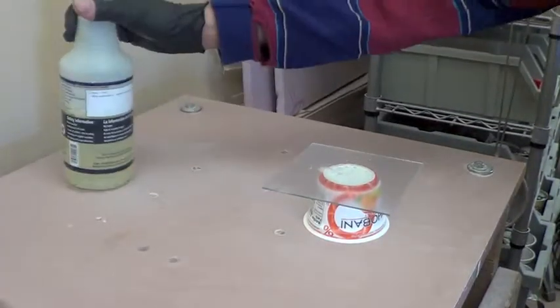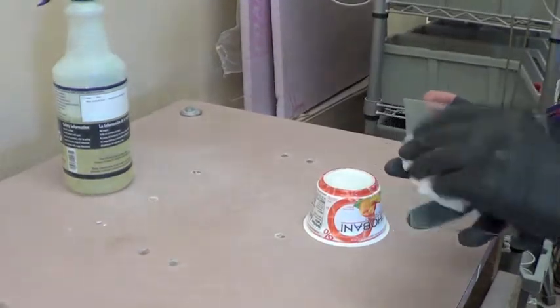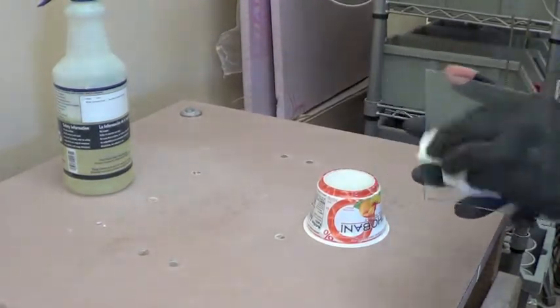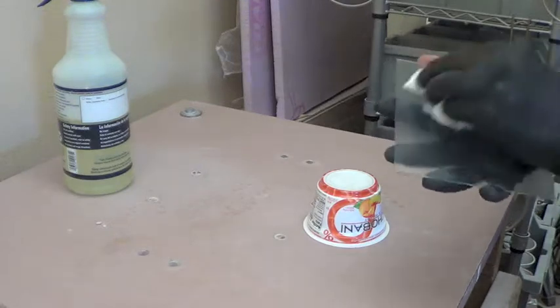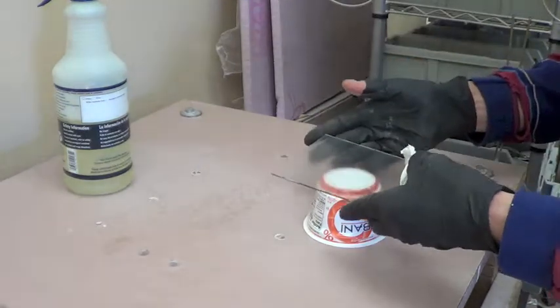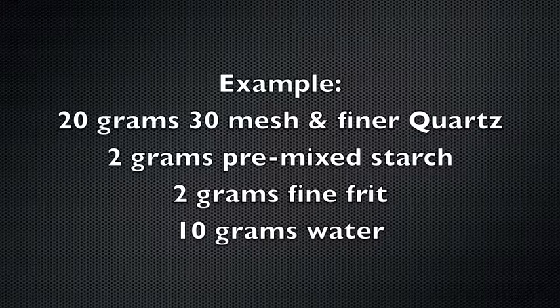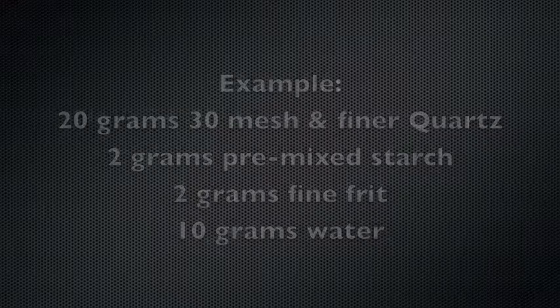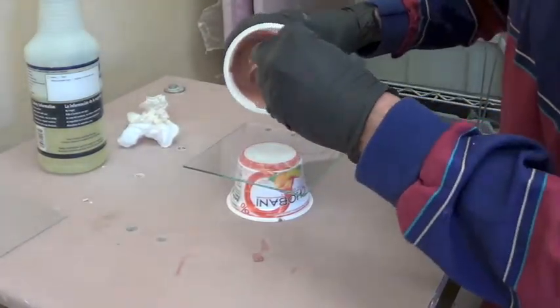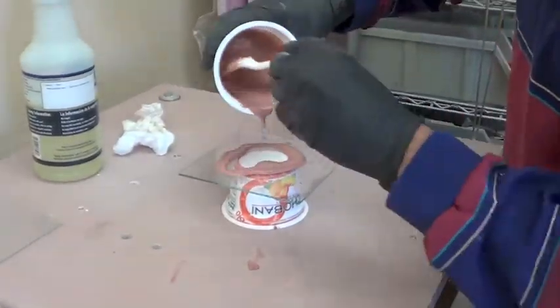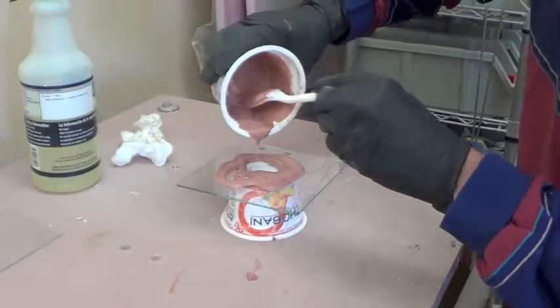First, wipe the glass with some diluted detergent. This keeps the mixture from pooling. Then make the encapsulated mixture. This requires some testing to get the right proportions, but here's my mixture to make a 5x5 tile using crushed quartz rock from my yard. 20 grams of 30 mesh and finer quartz, 2 grams of premixed starch, 2 grams of fine frit, 10 grams of water. Make a slurry and pour it onto the pre-cut glass and level it. Put that on top of the kiln or in the sun to dry.